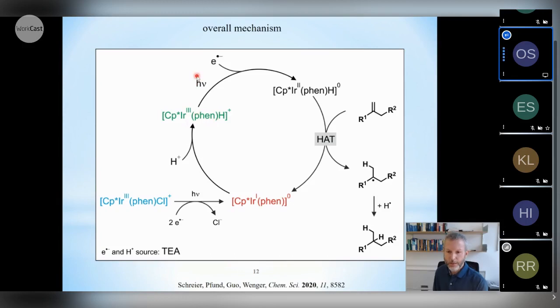Then promotion to the MLCT state leads to reductive excited state quenching. Presumably this is the highly reactive species which we have been unable to detect because it reacts so fast with substrates or just about anything, and you will get these radical intermediates, for which I have shown you indirect evidence at the very beginning through the radical clock experiment and also through the product yield radical stability correlations.